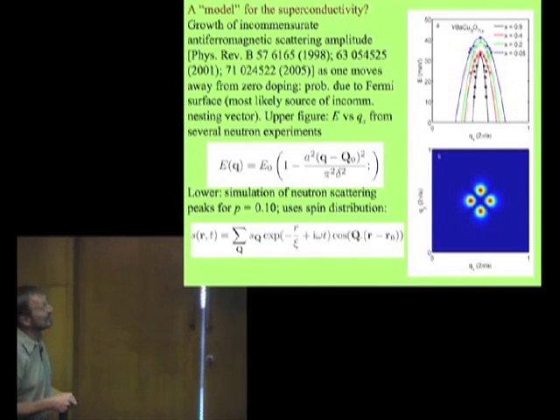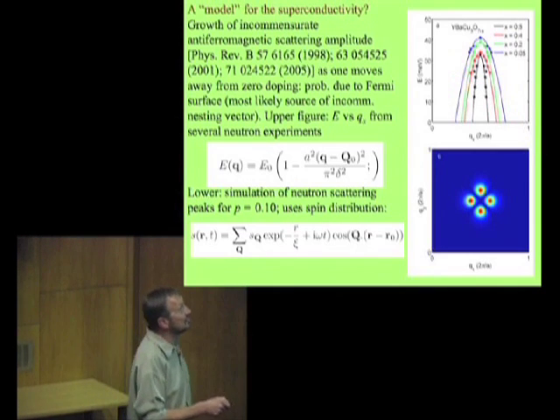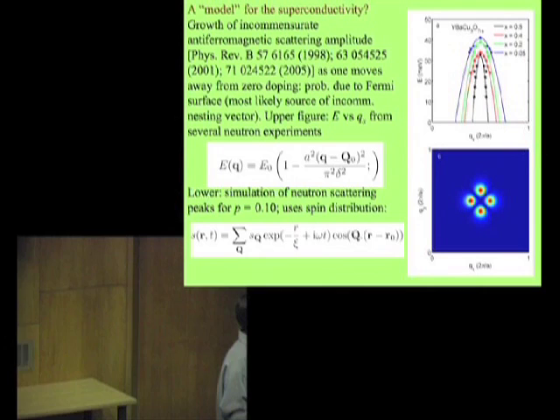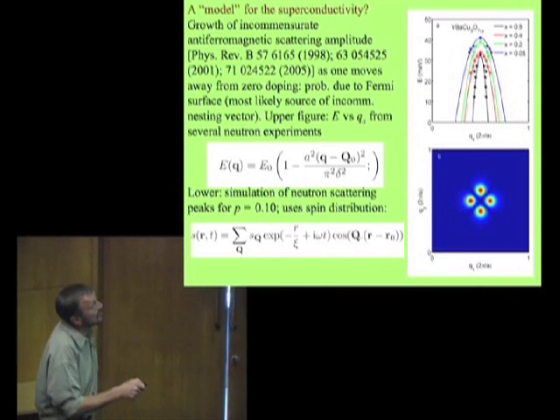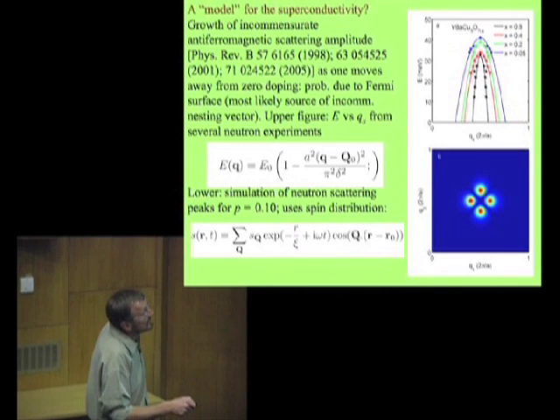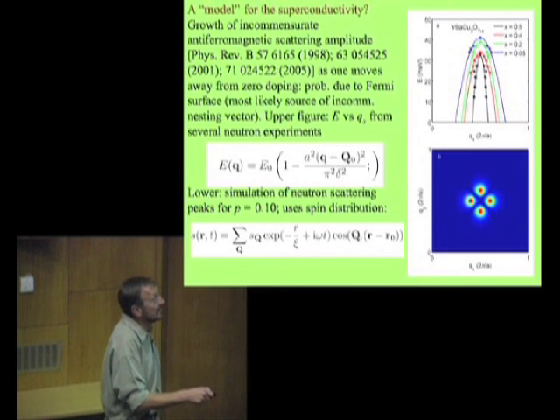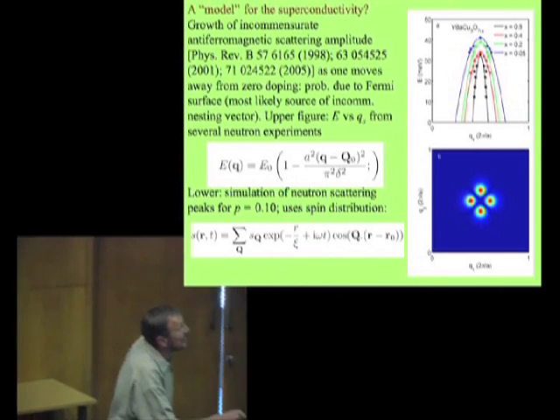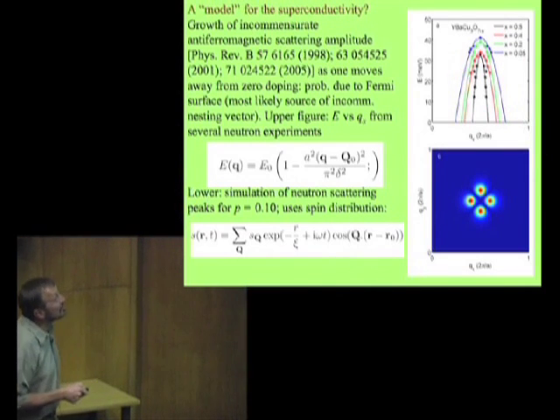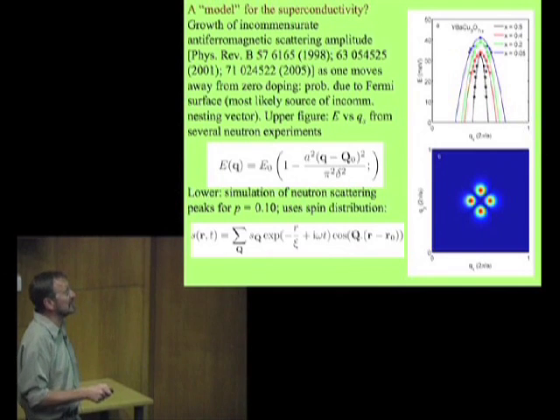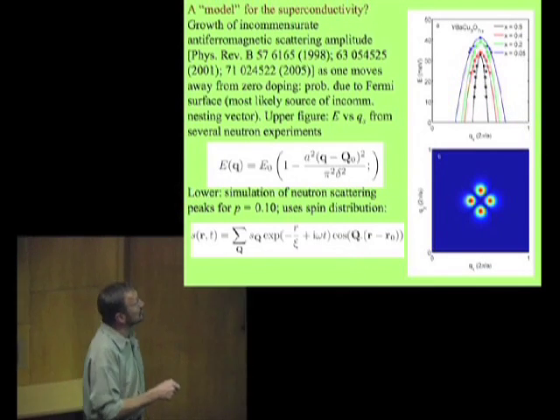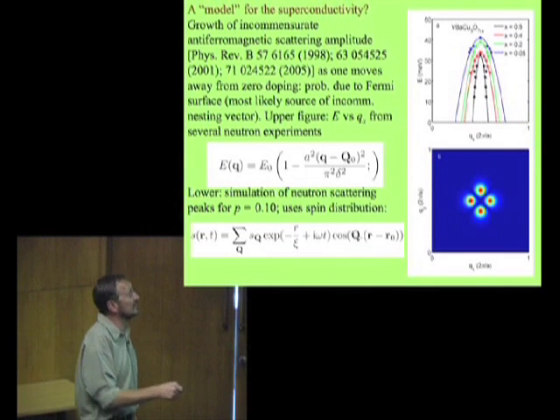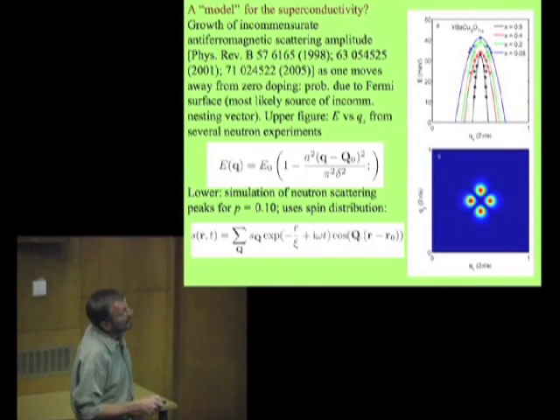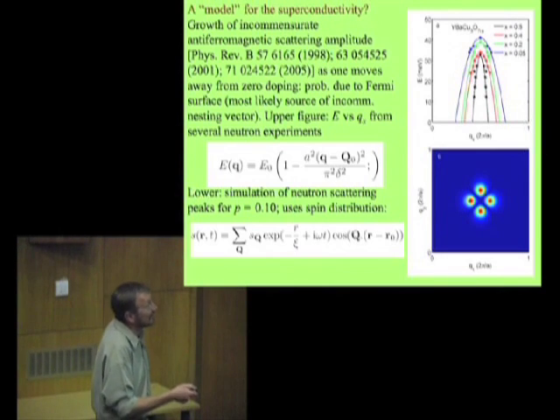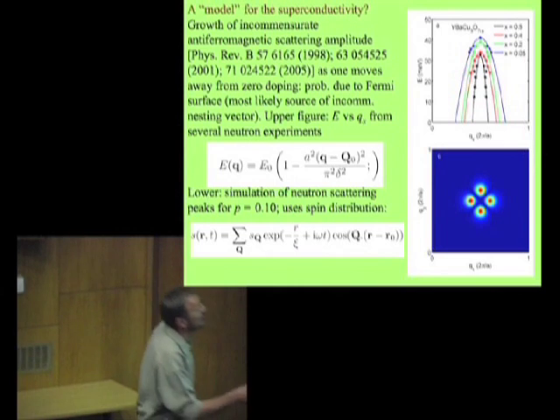Now, what we have to do is to be able to simulate the neutron scattering. These are simulated neutron scattering data with scattering intensities, red being intense, blue being low intensity. And you can see once we look at this thing in 2 dimensions, you're getting peaks corresponding to these regions where the dispersion curves touch down at these points here. Not at 0 wave vector, but out in the Brillouin zone. So we simulate these neutron scattering data using a static spin distribution, which has again this correlation length in it, xi, and which gives us something that reproduces the scattering amplitude that the neutron scatterers get. And this is a functional form of that.